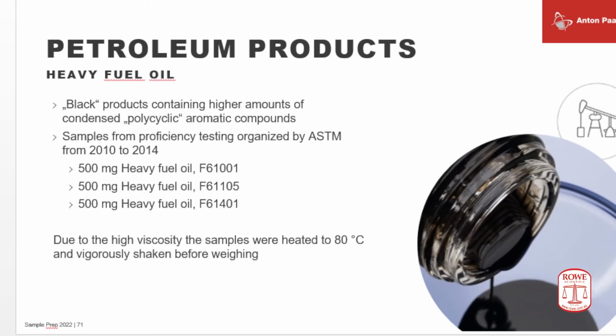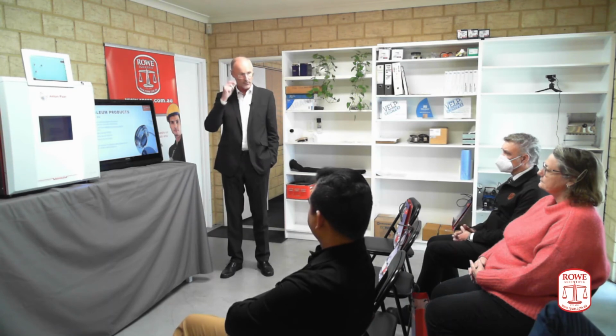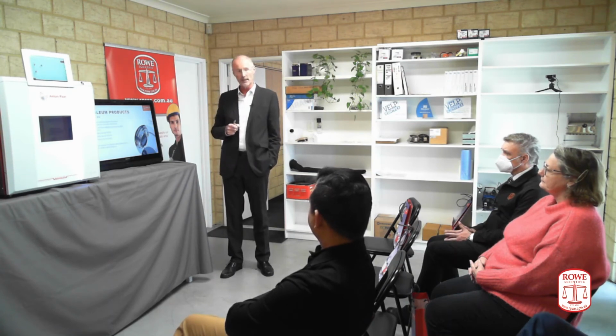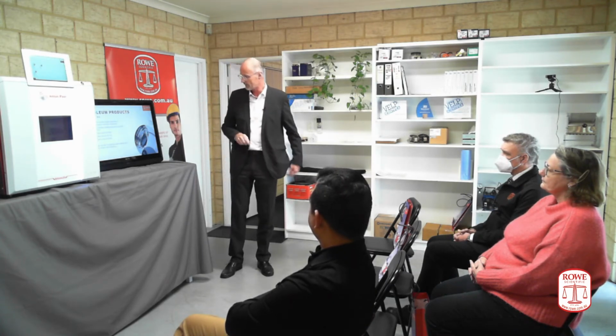Nevertheless, our trial was with 500 milligram, and in order to get these samples into the reaction vial, it was necessary to heat and stir the sample material before we were able to transfer it into the reaction vial. We typically do this with Pasteur pipettes that you can throw away after the dosage of the sample.